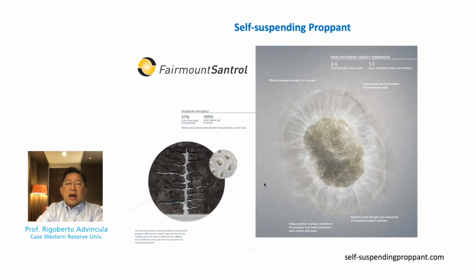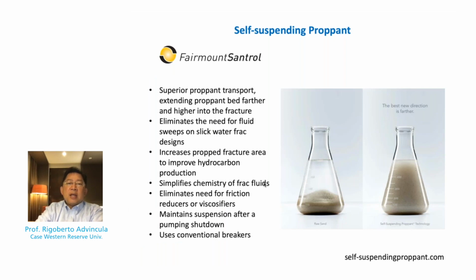So in this case, a gel, a hydrogel, or actually a polyelectrolyte complex surrounds the proppants, and therefore it is able to float. It's able to disperse more homogeneously on the frac fluid, and therefore stays longer and ends up in the fracture zone. So one can see here in this simple demonstration that a typical sand will simply settle at the bottom. But if the same sand can be coated with a gel or basically a shell that swells with water, it floats. Basically, it viscosifies the fluid too. In other words, one possibility is the need for less friction reducers and viscosifier on the frac fluid because the viscosifying media actually surrounds the particle or sand itself.